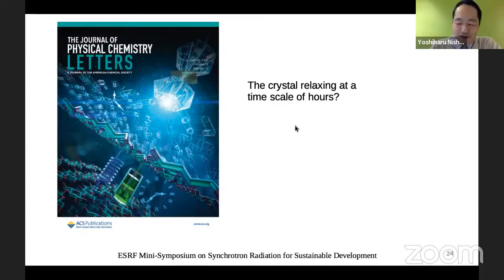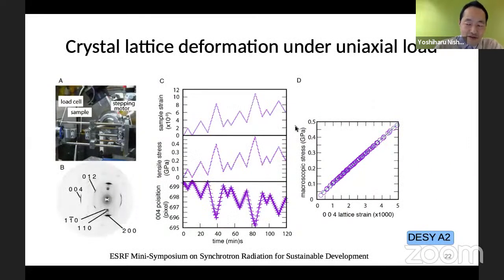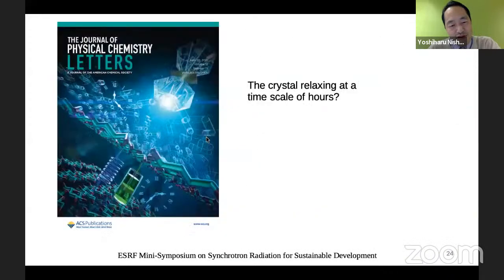And what was surprising was that in both uniaxial load and hydrostatic pressure, there seemed to be a time dependence. So here what we have done is a cyclic loading. If you take this small cycle and look at the elastic behavior, or if you look at the longer run behavior, the values were not the same. Here, this is an artistic illustration of what we think is happening: the crystal is actually relaxing at the time scale of hours. So it was a little more complicated than what we thought at the beginning to understand the crystal in the continuum mechanics framework.